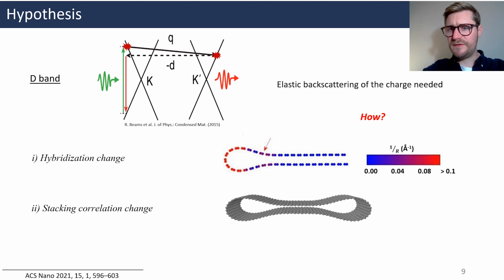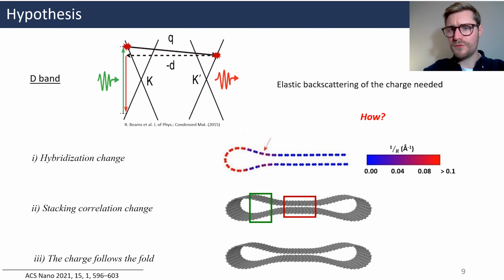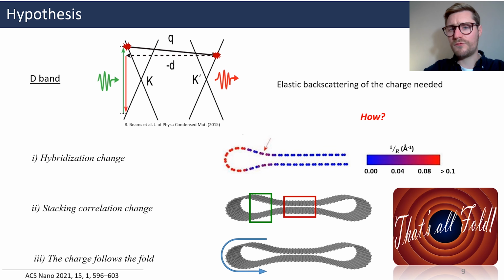The second hypothesis involves the same kind of energy barrier near the cavities, but instead of coming from the hybridization change, it comes from the change of stacking correlation in between the central zone and the cavities. Finally, the charge could simply follow the cavity by turning around the fold to recombine with the charge above. We were not able to elucidate which of those mechanisms have a major contribution to the signal, but regardless, they all come from the fold.